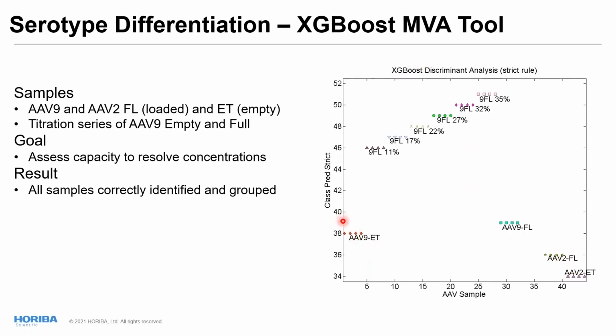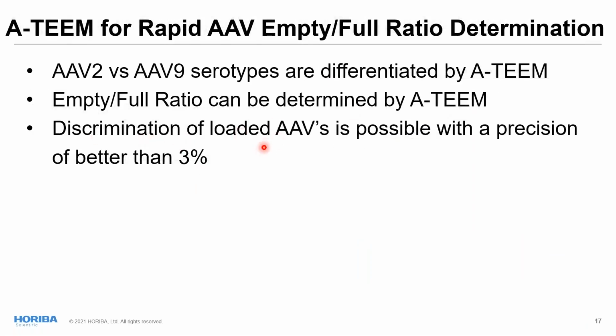And the class prediction, so essentially where they fall on this y-axis, shows that we're able to differentiate between these 4 samples. And we also added the titration sequence of the full versus empty, and this was done with just the AAV9 sample, and we're able to see good differentiation between all of these samples. So all of the samples were correctly identified and grouped. We were able to resolve not only the concentrations, but also the different serotypes. And with discrimination, this is kind of summarizing that, the discrimination of the loaded AAVs, at least with that titration sequence that we ran, has a precision of better than 3%.